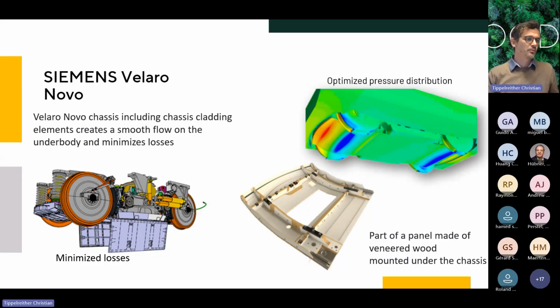So we developed a whole panel. It's a 3D pressed panel also with a system to enlarge the stiffness behind it. With this part we optimized the whole pressure and the energy consumption of the train. So when the train is driving up to 300 kilometers per hour, a lot of pressure comes up at the front part of this bogie. And so this wooden part has to cover this whole energy also. And with this aerodynamic part, the train can reduce the energy consumption by up to 15%. It's really quite high.